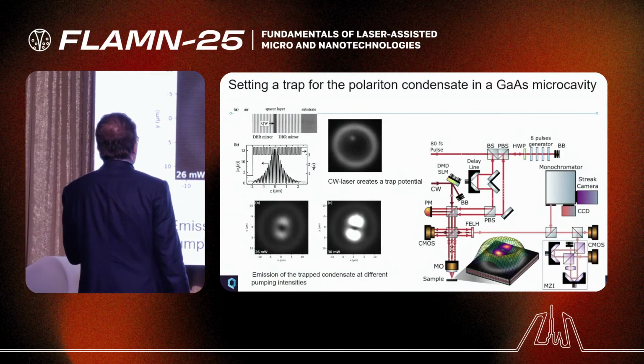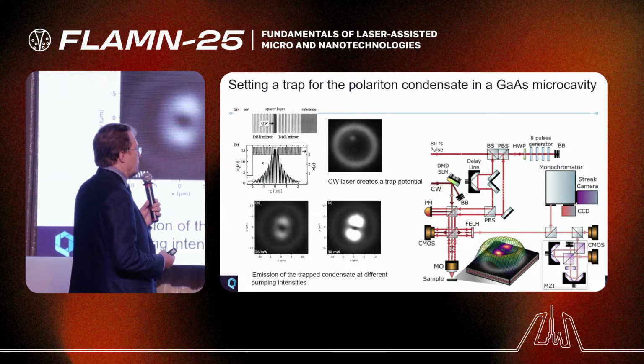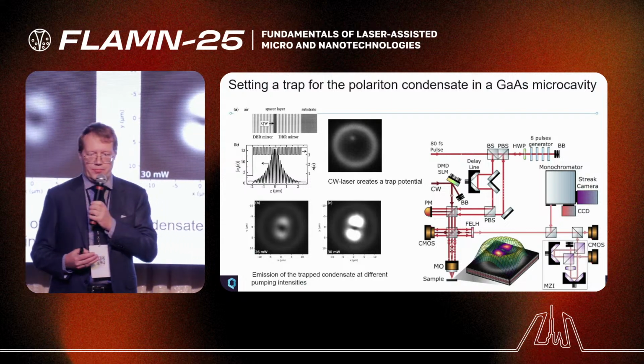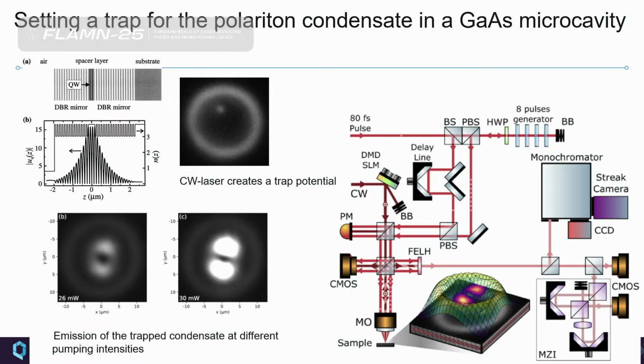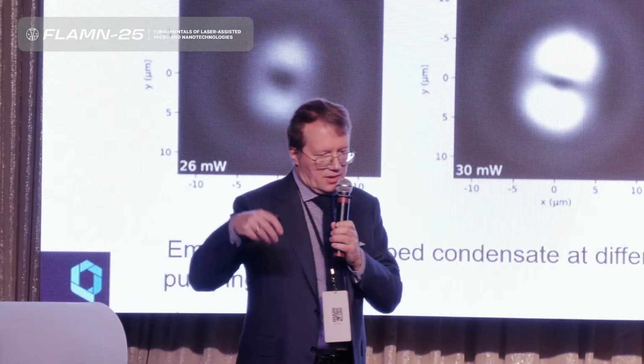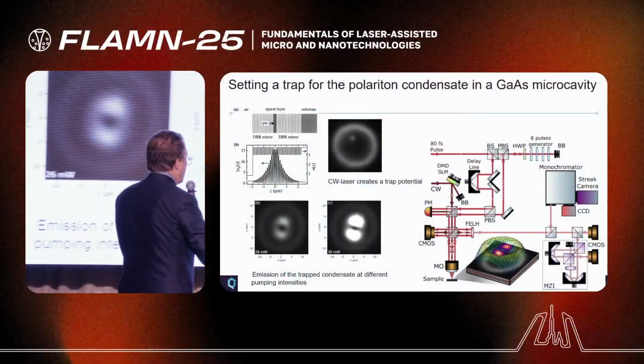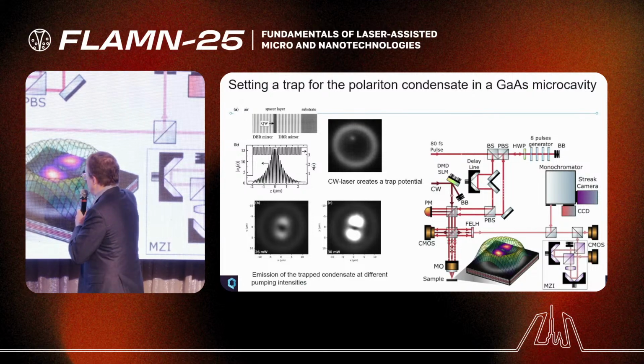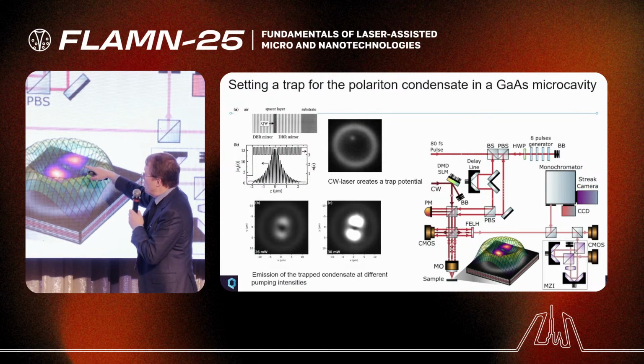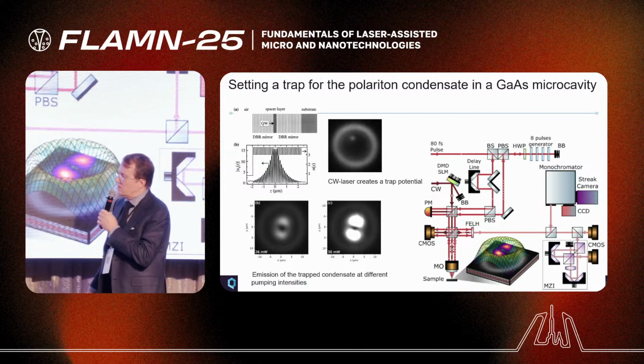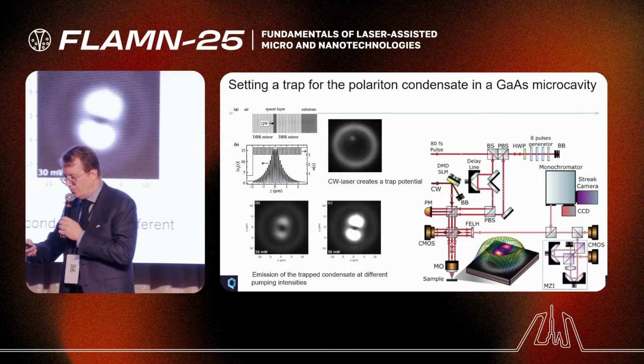So now what happens experimentally? Experimentally, first of all, you need to create a trap, right? To have this ring condensate, you should create a trap. You can do it in different ways, but the most flexible traps are created optically by non-resonant laser light. With a spatial light modulator, you create a potential in the shape of a ring, and this excitation creates a cloud of electrons and holes. They repel polaritons. So for polaritons, it is this kind of structure, like a stadium. Yes, this is a trap. And there is quantization of polaritons inside the trap, and you can study quantized states, choose 2 of them and make a qubit in the trap.